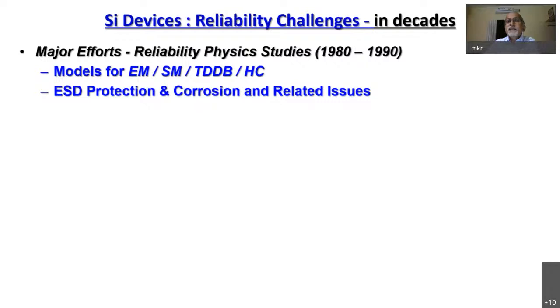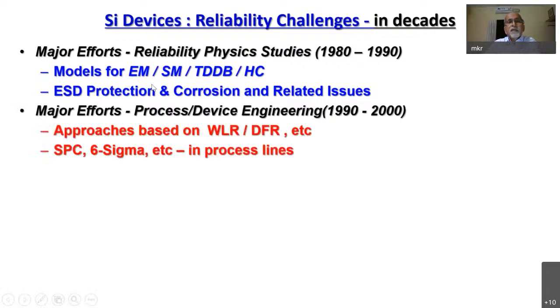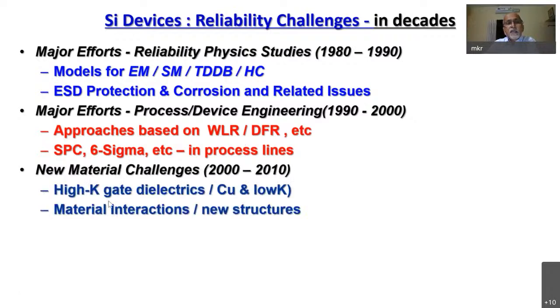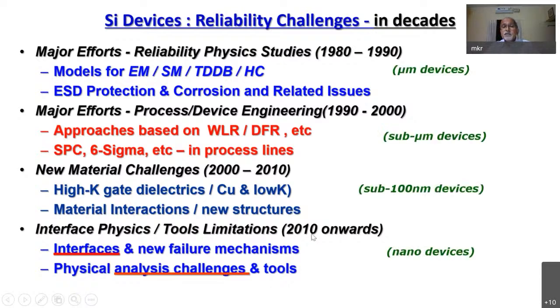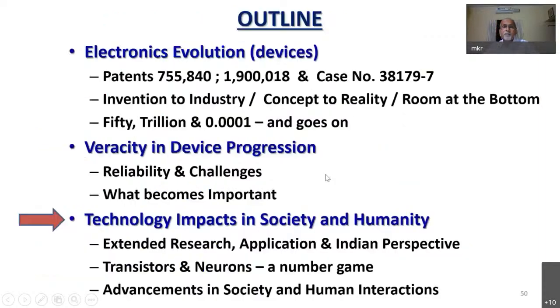Reliability challenges in the 80s and 90s were electromigration, dielectric breakdown, ESD protection, etc. The approach in 1990 was based on the fab, Six Sigma process and SPC. Then the new material challenges arose, using high-K gate dielectrics, oxide dielectrics for the interlayer, then material interactions and new structures. In 2010 onwards, interface and analysis challenges came for micro devices, sub-micron, sub-100 nanometer, and nano devices. So as technology improves, our challenges also vary, and so do the studies.